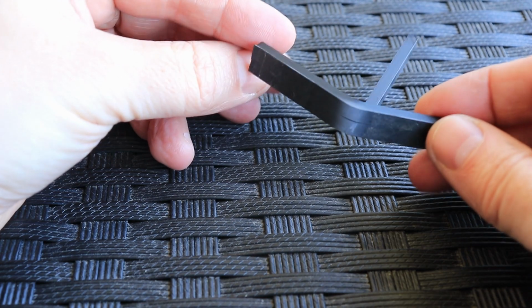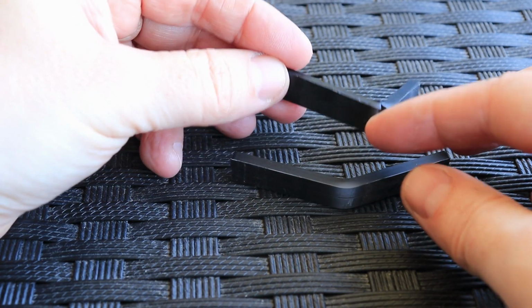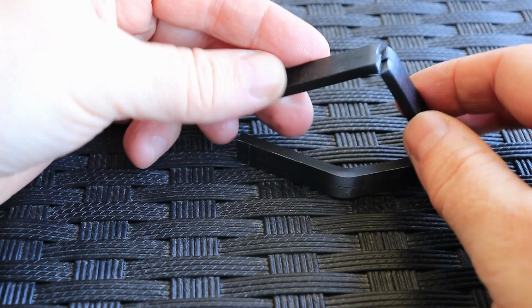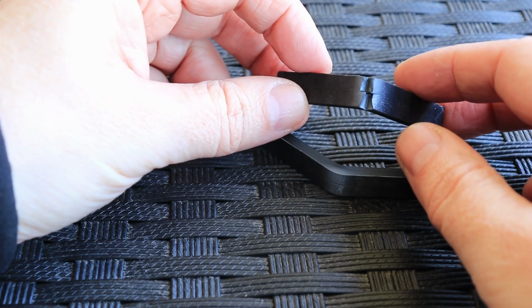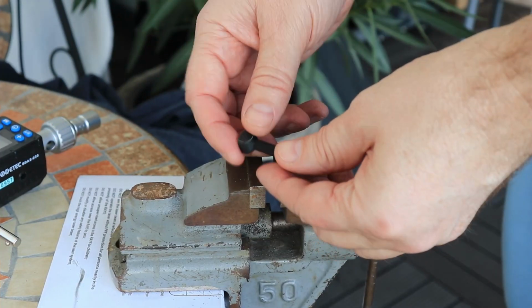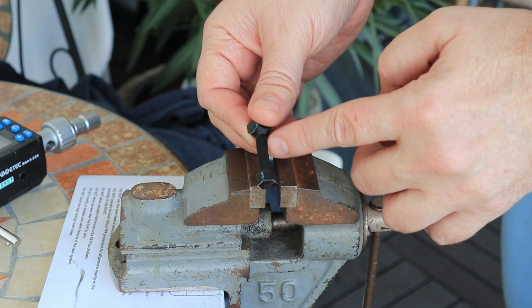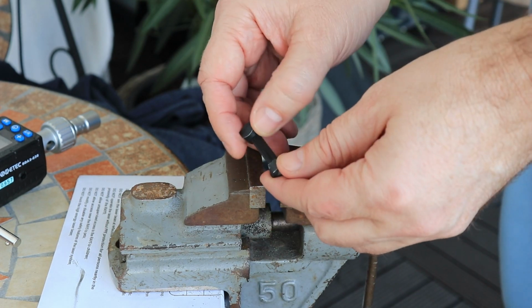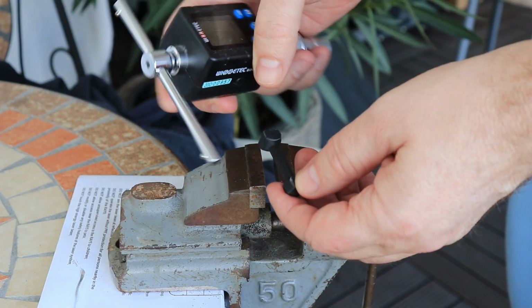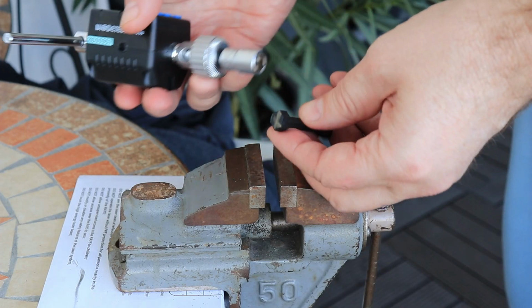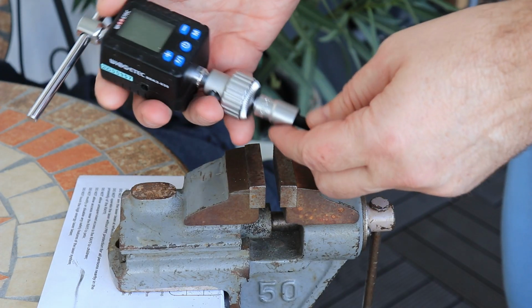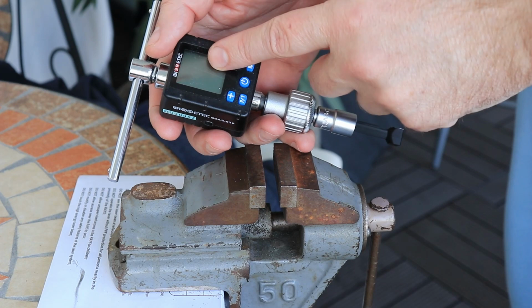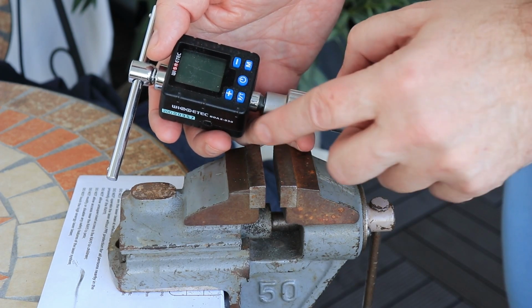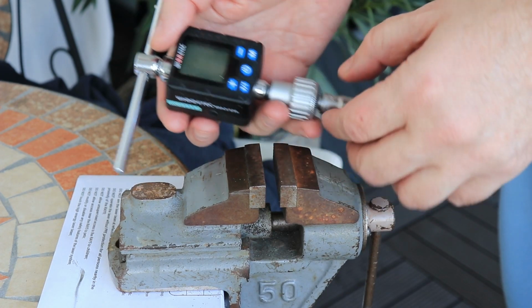The ABS Plus didn't break, just deformed, but the ASA broke. Not completely, but partly fractured. And for this torque or twist test, I have test specimens with a diameter of 6 mm and a length of 22 mm. This side goes into the vise, and the other side goes to this wrench torque meter, and I will record the torque at 90-degree rotation and the maximal torque.